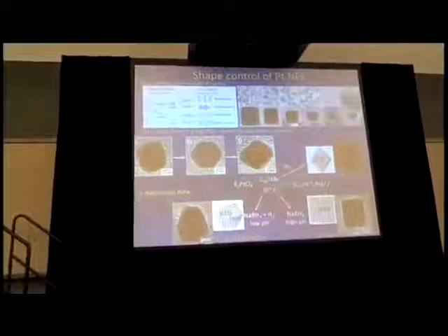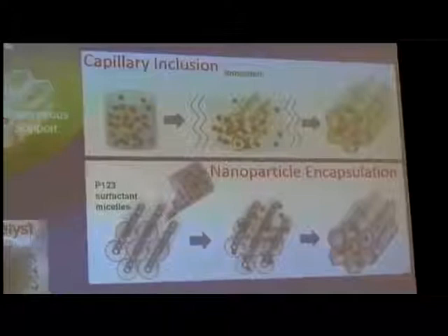When you change the size, you can also change the shape, and both are catalytically very significant. You can do it in two dimensions with Langmuir-Blodgett formation of nanoparticles in various concentrations, or by sonication or other ways, and put them into a mesoporous material to go three-dimensional. What is very interesting and well-known now is that by hard templating — as opposed to soft templating — you can take a mesoporous silica like SBA-15 or MCF-17 and produce mesoporous transition metal oxide supports.